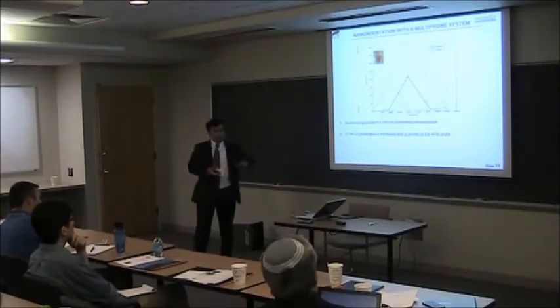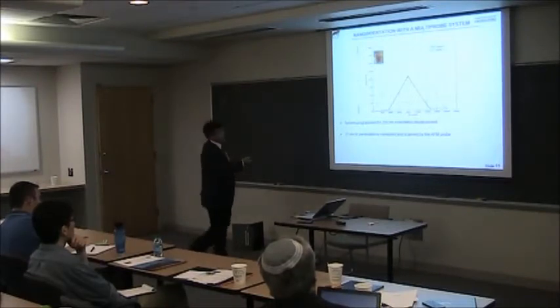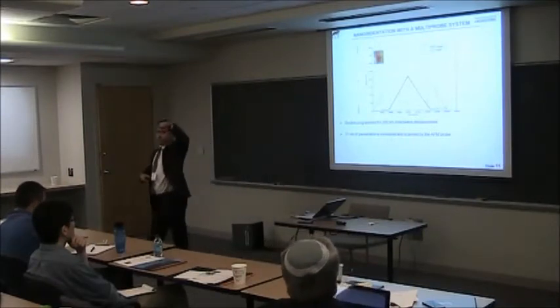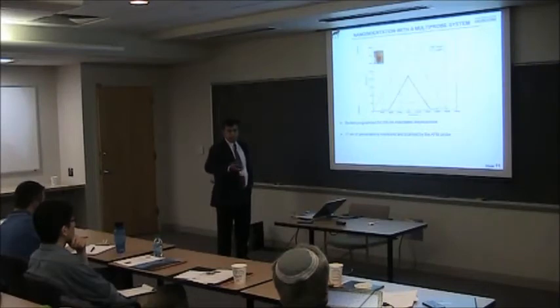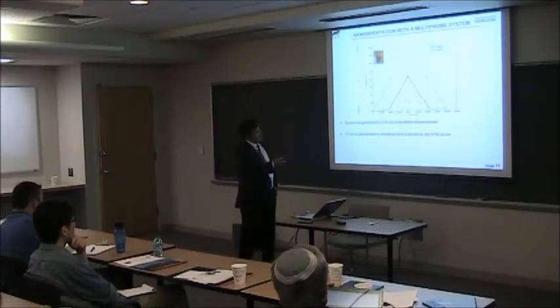Now, here's what we got from our initial measurements. So this red line is actually, it says 0 to 200, but I put these just to make sure. What happens is you go down first, 200 nanometer, and then go up until you touch the diamond, and then push the diamond up about 200 nanometer. Now, this is the stage value, so 0 to 400 nanometer. In the actual physical world, this is minus 200 nanometer to 200 nanometer. The blue line, on the other hand, is the tip on top of the diamond, measuring the displacement. See, it's 0 here because the stage didn't touch the diamond yet. And as soon as it touches the diamond, it starts moving up, around 200, and then going down. Now, if there is a plastic deformation, that may not be 200, it would be less. And then once we go down and still measure, here you can actually read some value for HF before even scanning your indentation.